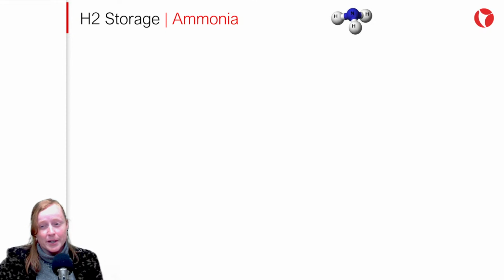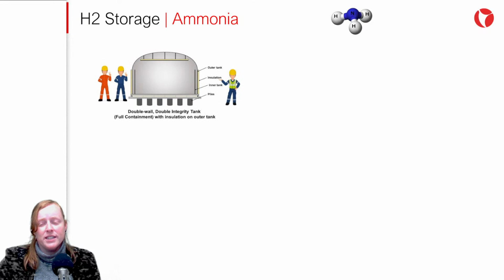So, how is ammonia stored? Well, there are different tank structures that can be used to store ammonia. In the past, they were made with single walls with internal or external insulation. The current standard based on quantitative risk assessment is to use double walls. According to statistics from the UK, the frequency of failure with double walls is 100 times lower than with single walls. The double-walled, double-integrity tank with external insulation shown in this figure would allow the tank to operate longer until repaired in case of a failure.